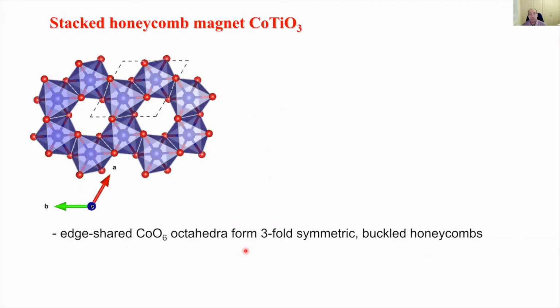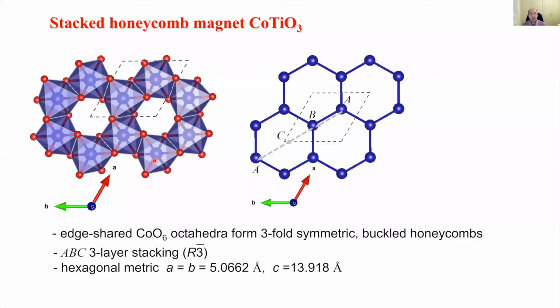So we're going to explore this physics in the context of a honeycomb ferromagnet, cobalt titanium oxide, where the building blocks are a honeycomb lattice of cobalt ions. These are the blue balls here. Each one is inside an oxygen 6 octahedron, and these octahedra are edge sharing. And they naturally form this edge sharing bonding geometry, giving rise to a honeycomb. And then successive layers are stacked up along the vertical direction. Say if we pick an origin of the honeycomb here, then the next layer would have the origin at this site here, the next one there, and so on. So there's a 3-layer periodicity along the vertical direction.